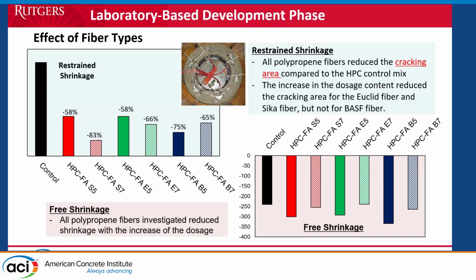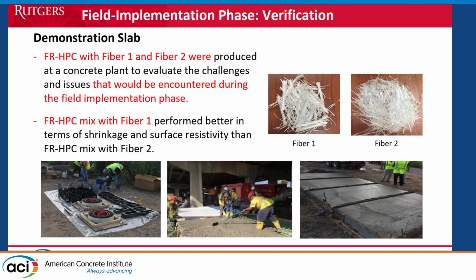If you look at the reduction in cracking, based on the lab at this point, you can see all of the mixes produced a reduction in cracking by adding the fibers. The maximum we got was about 83% reduction. The free shrinkage was also reduced drastically. So we were doing well on the shrinkage and well on the cracking. Once we selected one of the good candidate mixes, we talked to the contractor and asked them to mobilize as if they were doing it for the deck, and we put some slabs right underneath the bridge.